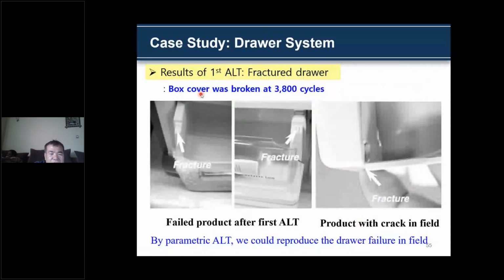The box cover is broken at the 3,800 cycles. This is the failure of the first parametric ALT. This is the result of the in-field crack. We found a lot of fractures of the drawer system. By parametric ALT, we can reproduce the drawer failure in the field.